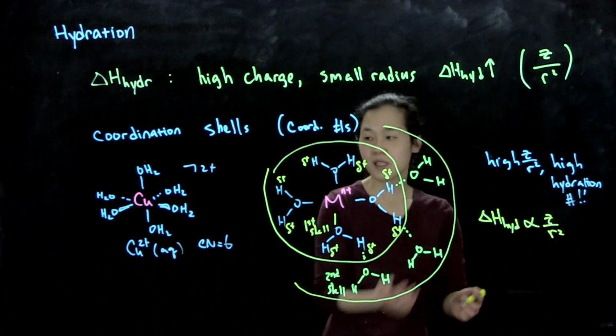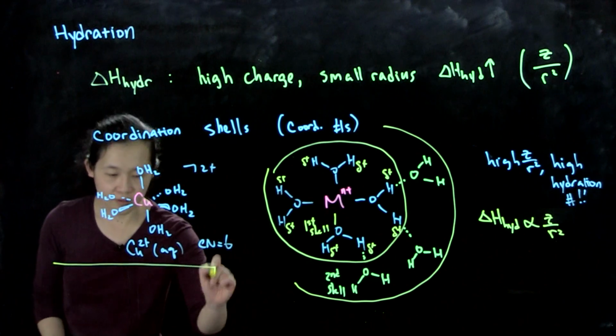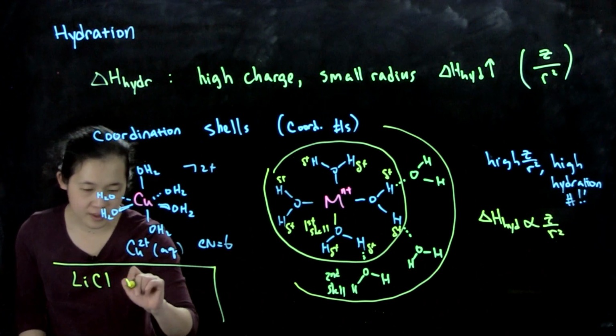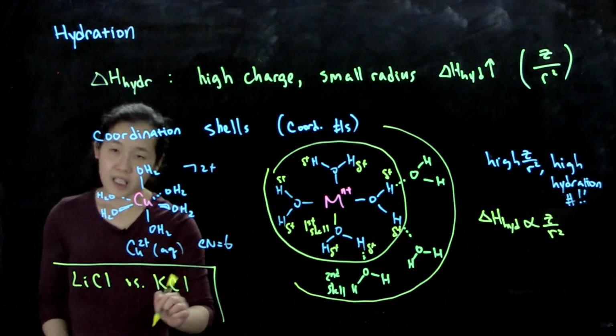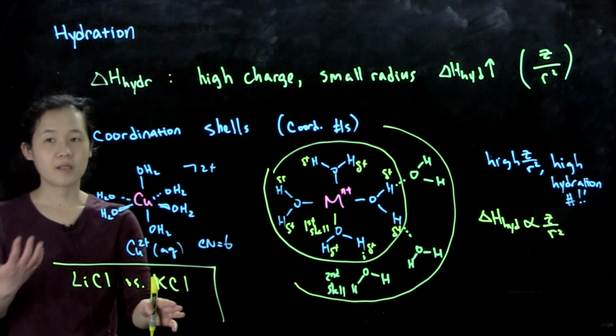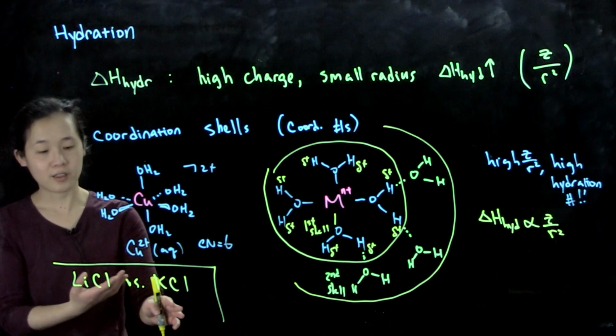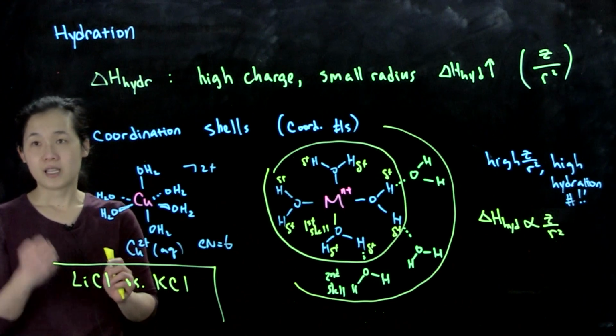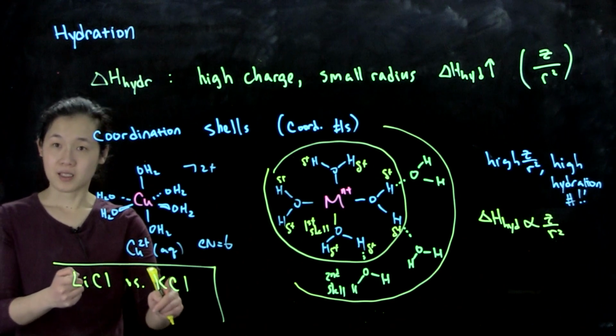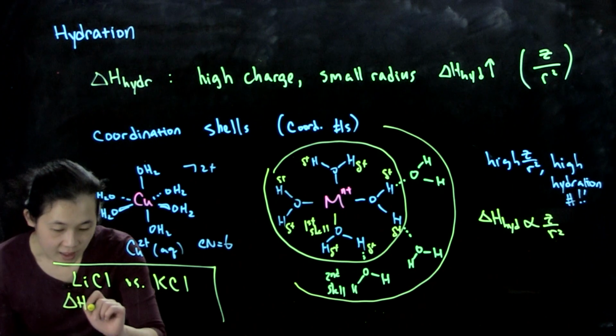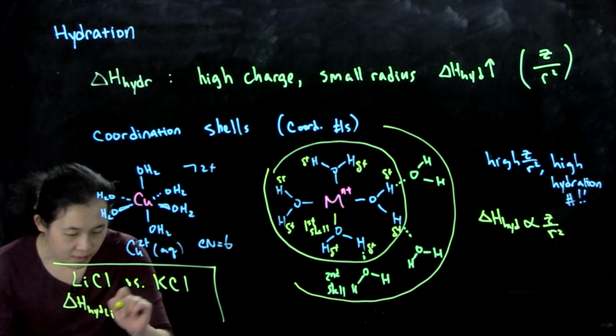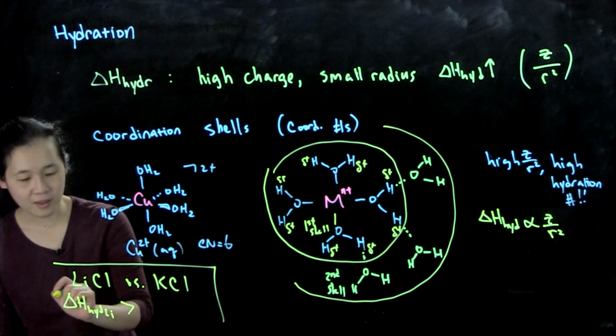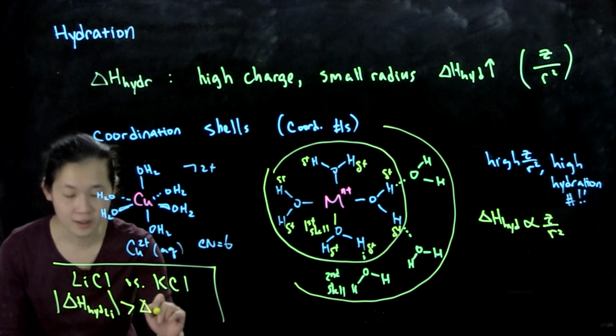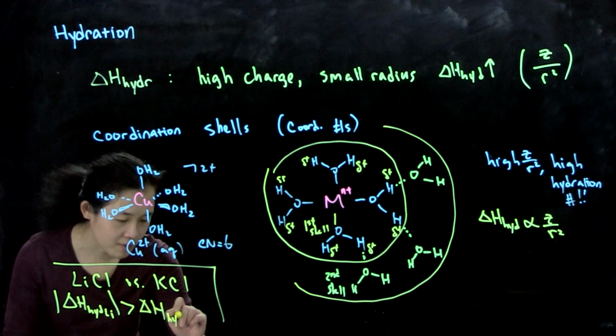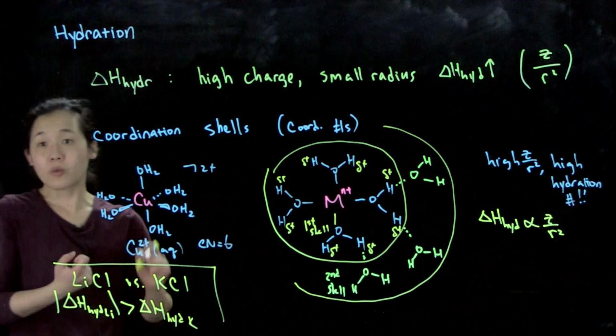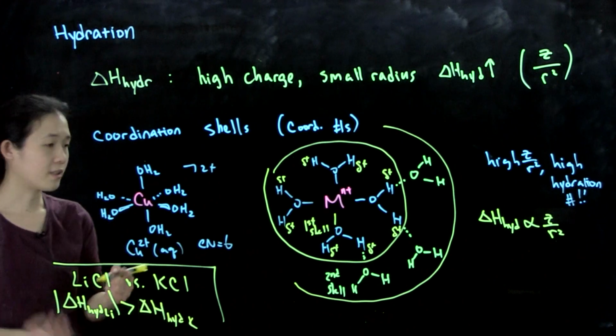And so as a result, if we're comparing the solubility of lithium chloride versus potassium chloride, even though potassium chloride is more polar, and you might think it should be more soluble in a polar solvent like water, lithium chloride has that high hydration number of lithium compared to potassium. So what we're saying is the enthalpy of hydration of lithium is greater, I meant greater in magnitude. It's more negative than the enthalpy of hydration of potassium. And so lithium chloride is actually more soluble than potassium chloride in water.